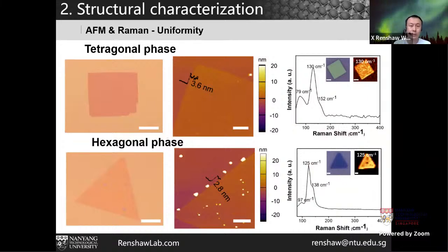So what we generally do, of course, first is the structural characterizations to see whether they are really tetragonal phase or hexagonal phase. To be specific, we need to know whether they are uniform, right? We get a flake. Then we need to know whether they are really everywhere tetragonal phase or everywhere hexagonal phase. So we did, of course, the AFM to measure the thicknesses, also the Raman to see whether they are structurally uniform. Especially for the Raman measurement, if you look at the right top images, this is the Raman scanning, so you can see that over the wide range of the whole flake, the phase is uniform.